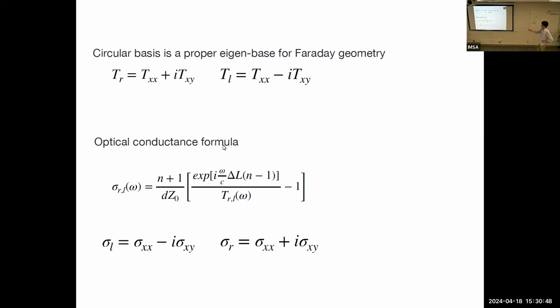So, first of all, we're talking about light matter interaction, so the proper basis is not the XY basis, but the right and left circularly polarized basis. So we measure this transmission matrix, TXY, TXX, etc. We define right and left circularly polarized transmissions, and from that we can get the conductances for right and left circularly polarized light. And then if you do this transformation back, you can extract the sigma xy.